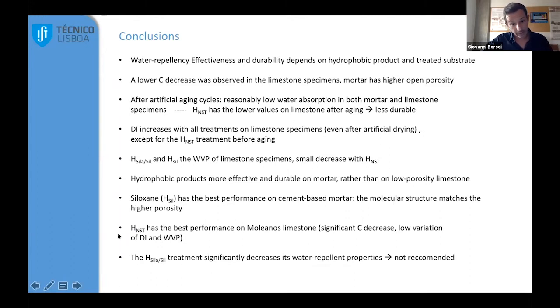On the other side, the nanostructure material is more effective on the limestone, because it gives a significant reduction of the water capillary absorption, but a very low reduction of the drying index and of the water vapor permeability. So it is providing water repellency, but respecting the features of the original material. And finally, we cannot recommend the use of this siloxane-silane product, because it is strongly affecting all the features of the moisture transport properties.